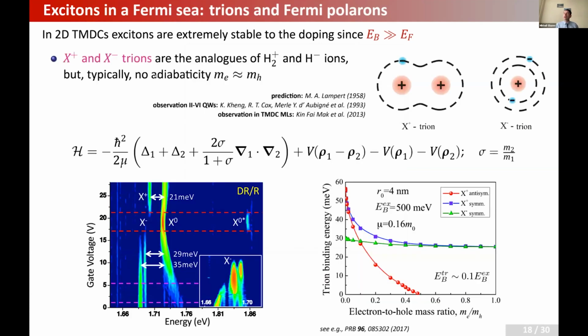So these trions are routinely observed in transition metal dichalcogenides, and they have relatively high binding energies. Typically the binding energy of the trion is something like 10% of the exciton binding energy. So it should be something on the order of 20 to 30 milli-electron volts in this case. And indeed, for instance, if you add some doping, you add more holes or you add more electrons,